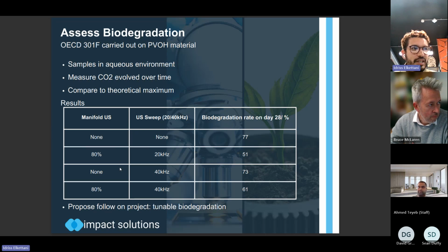We did a further 2 tests. So the first two samples were done at 190 degrees, and the second 2 were done at 170. And you can see that for the same ultrasonic parameters, we're increasing the sweep from 20 to 40 kilohertz. We've managed to bump up the biodegradation rate back to 61%.